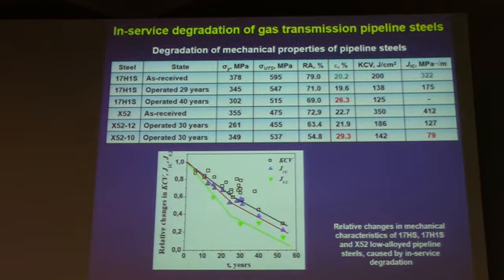Here you can see mechanical properties of pipeline steels in as-received state and after operation. It can be seen that after long-term operation, strength properties were decreased, and the characteristics of brittle fracture resistance were sharply decreased. So these characteristics can be used as mechanical parameters for evaluation of the degradation degree of pipeline steels during operation. And for further investigations, we used impact strength as a characteristic practically always put in regulating documents.